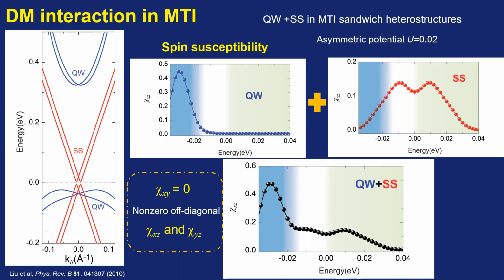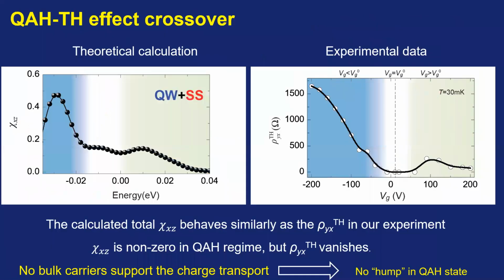This is the surface state contribution. It shows a double peak around the magnetic exchange gap regime. If we add them together, we get this kind of phenomenon. This phenomenon is very similar to our experimental observation. Let me compare these two, the experimental data and the theoretical calculation. This is the theoretical calculation. This is our experimental data.